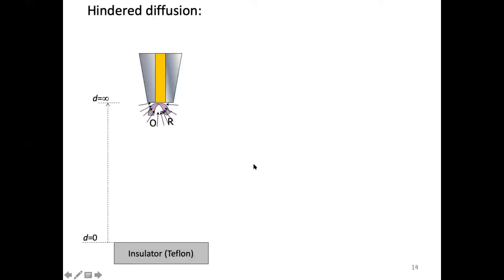Well, the interesting thing happens after this point. Now again I have an electrode, we say an ultramicroelectrode. I have the gold part, and now it is polarized. I applied sufficient negative potential so that O is getting reduced into R. Obviously there is going to be a steady state, and there is spherical diffusion as shown by the small arrows. Everything is going on as we discussed before, and we get a steady state response like this. This is current, this is potential, and i subscript T,infinity indicates tip current. Tip means the ultramicroelectrode current at infinite distance from the substrate.